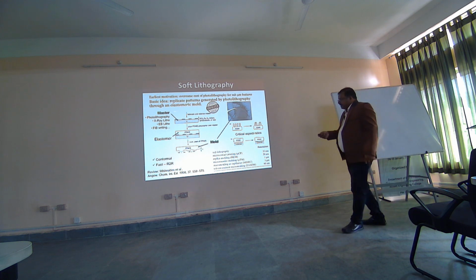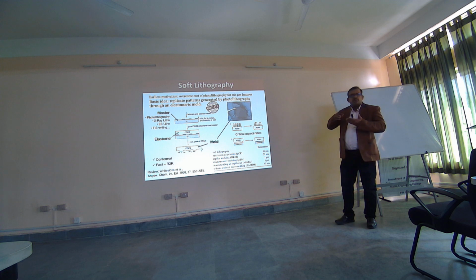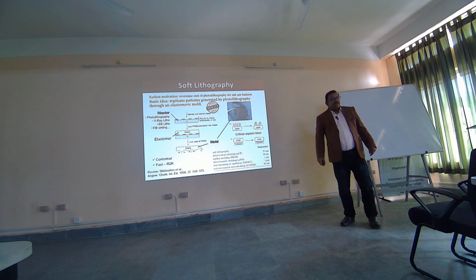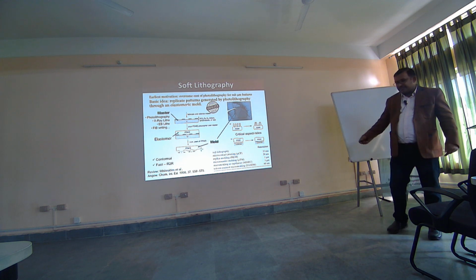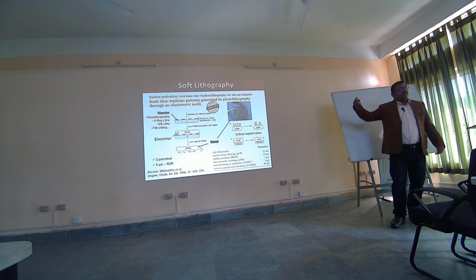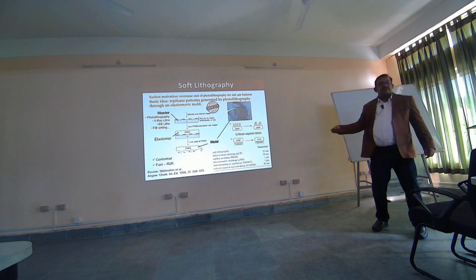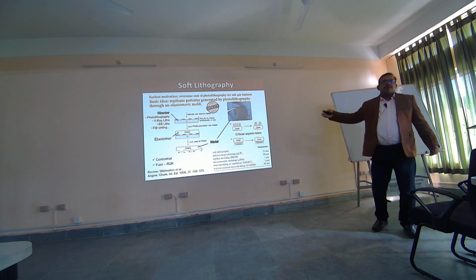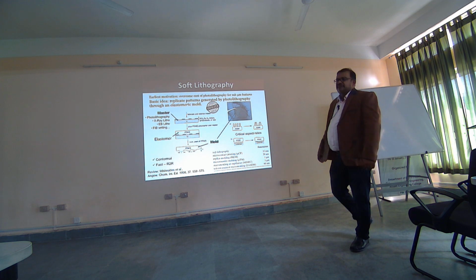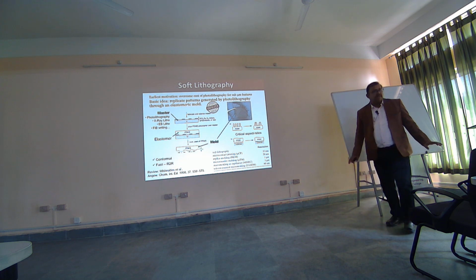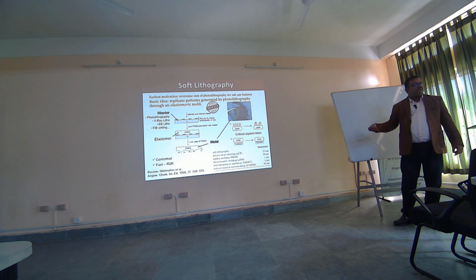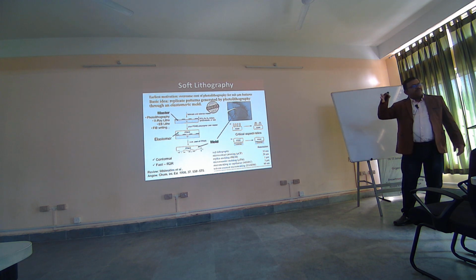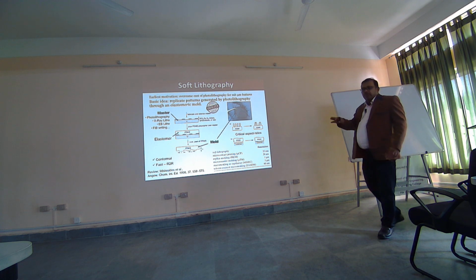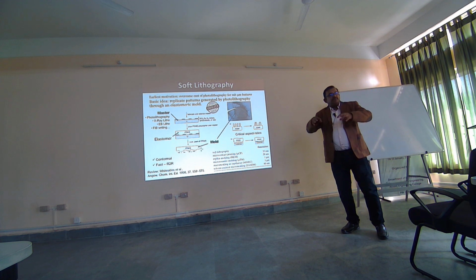Now, in these organic materials, since it is difficult to have that kind of 3D integration because these materials are soft and you cannot subject them to some kind of chemical agents and things like that, and the different stages and especially the oxidation. Oxidation usually happens at 1200, 1500 degrees Celsius temperatures. Most of the organic materials cannot sustain temperatures above 200, 250, 300 degrees Celsius at the max. Okay, because most of these materials, their glass transition temperature is ranging between 200 to 300. So basically, glass transition temperature means they will go into some kind of molten state.